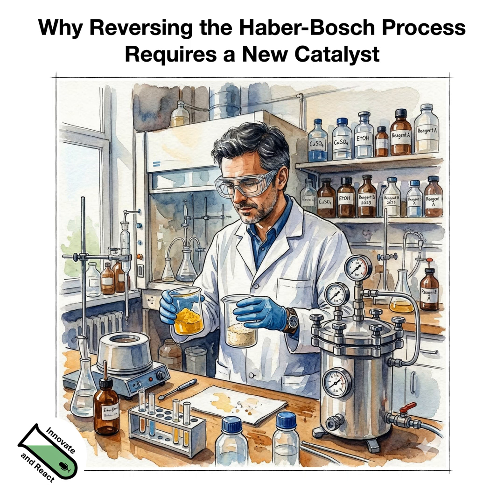So, for instance, as you mentioned, we have iron and cobalt, which we have already discussed to be the active phase in the final catalyst. And then we have these lower amount, like this 30% or something of magnesium oxide. Magnesium oxide would have the function as the support, stabilizing the metallic nanoparticles. And in order to obtain small particles of both the support component as well as the metal component, we need to intermix them as good as possible.